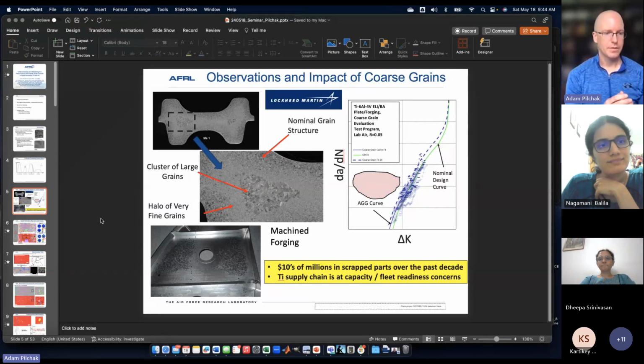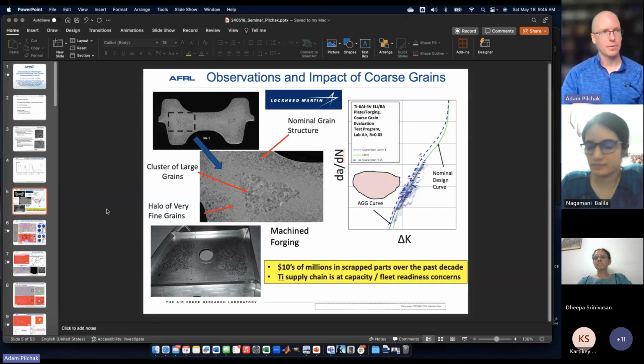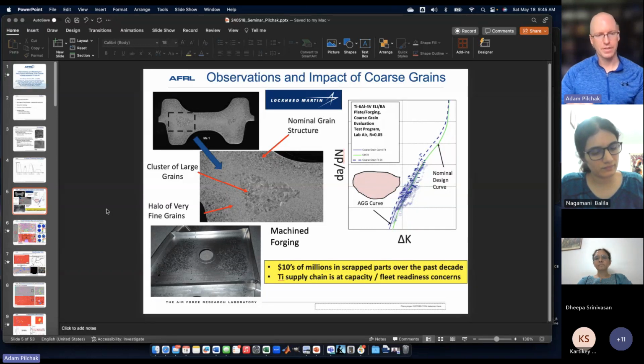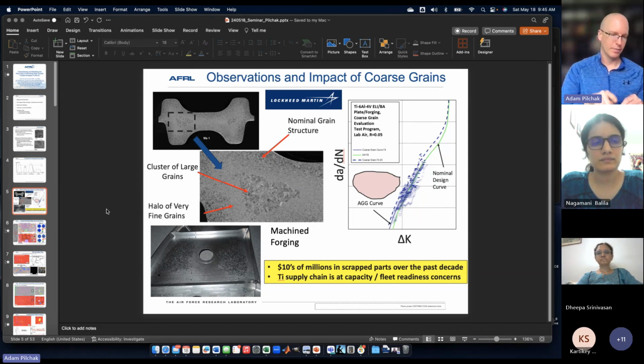There are now some nice convolutional neural network algorithms out there. I'm trying to remember the name of it, something like crack CNN, but it allows you to very easily segment the crack from the image data and develop pretty good measurements of crack growth rate. The downside with small crack measurements, or not downside, just a fact of running those experiments, is you need to estimate the aspect ratio of the crack. The surface crack length is interesting, but ultimately it's the crack going into the depth of the material that's important, and that's what you would use for any life prediction calculations.